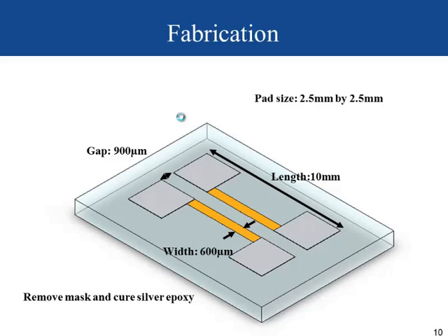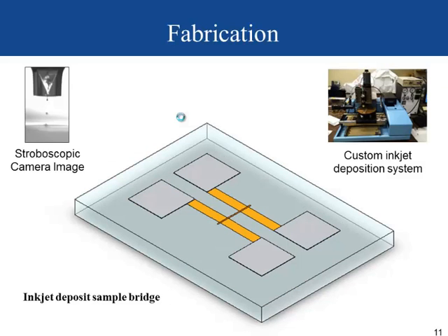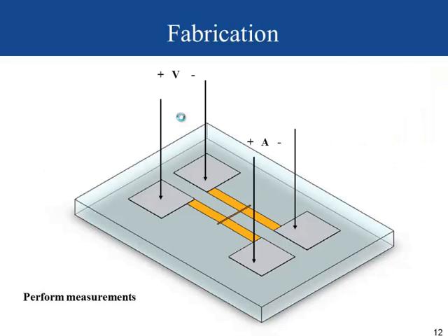This gives us the dimensions of our test structure used in this work, where the important one here is the gap between our two gold lines, which is 900 microns. Now, we can place this on our custom inkjet printer, and we can deposit our material of interest, in this case the gold nanoparticles, orthogonally across the test structure to form a bridge. Once we've done that, we can place this under measurement, and we can then interrogate the bridge.